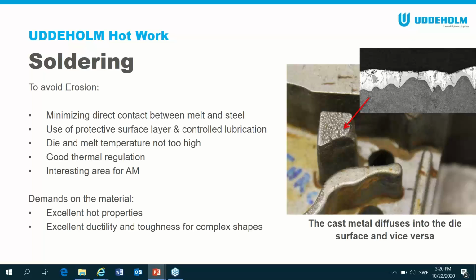And of course, you've got to try and minimize the contact between the melt and the tool steel because the melt wants to bond with the tool steel, which is what soldering is. So you need to put a protective layer there. So that normally can be a coating, it can be nitriding, or even good lubrication counts as well, of course. You want to try to avoid too high die temperature. We've got an extreme example here because this die's got so hot, it's making it worse. And unfortunately, there's no conformal cooling in this die.